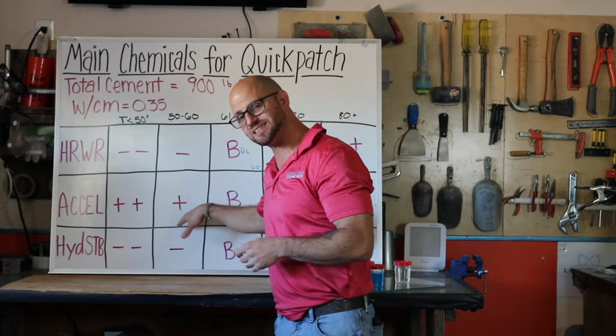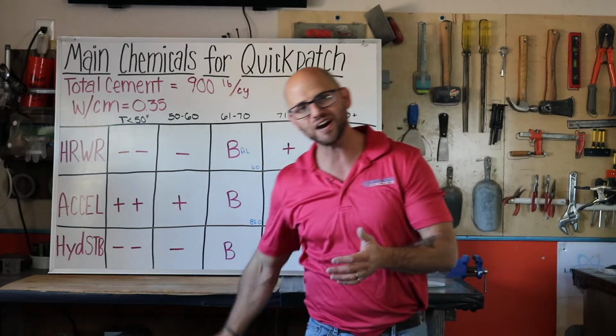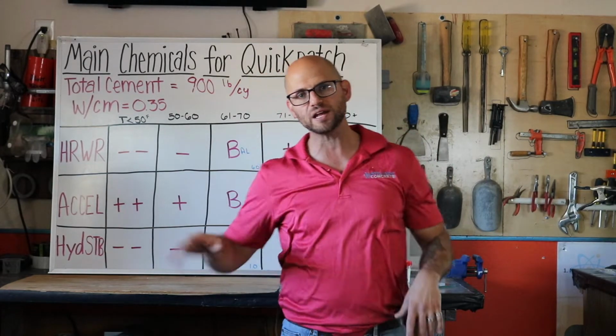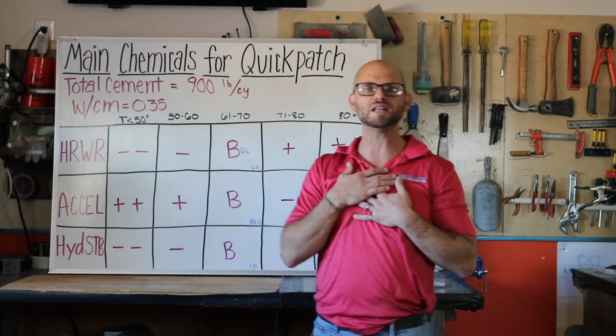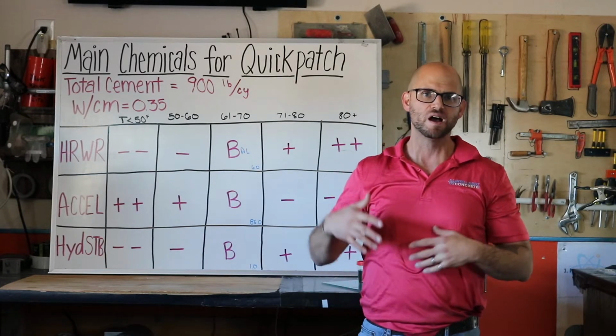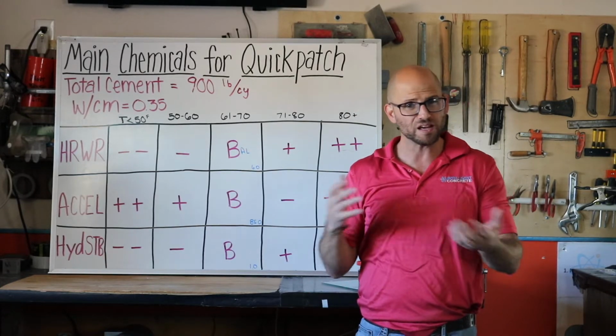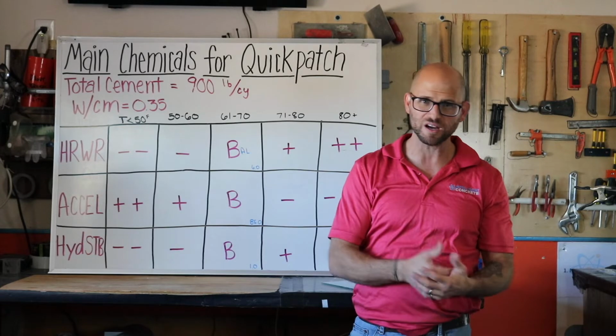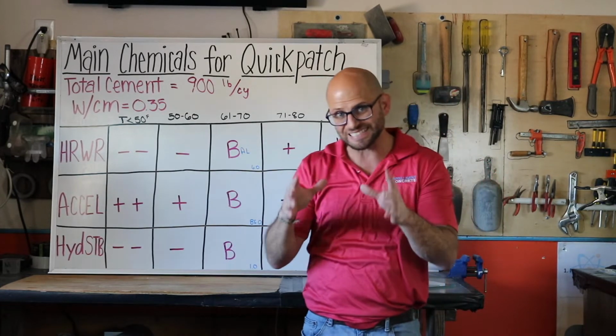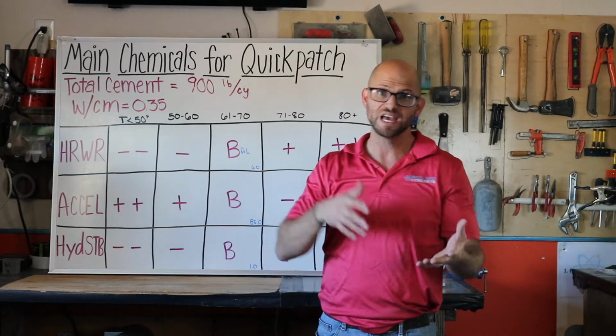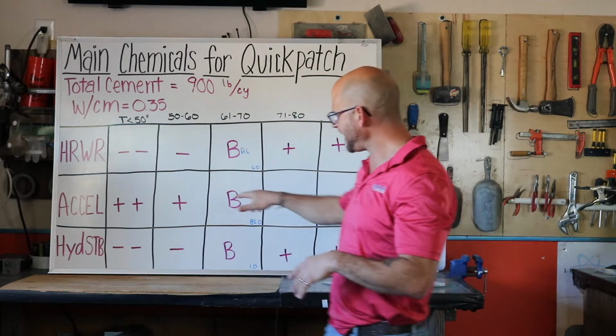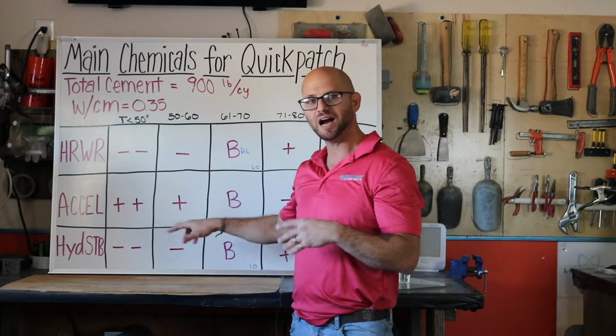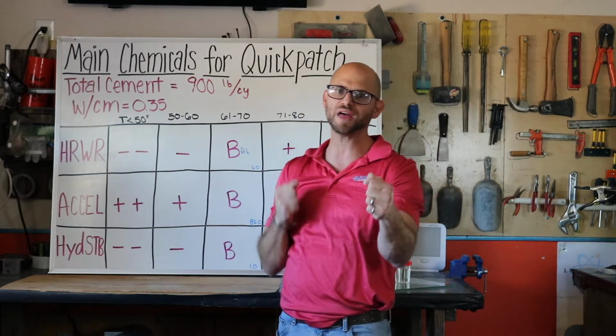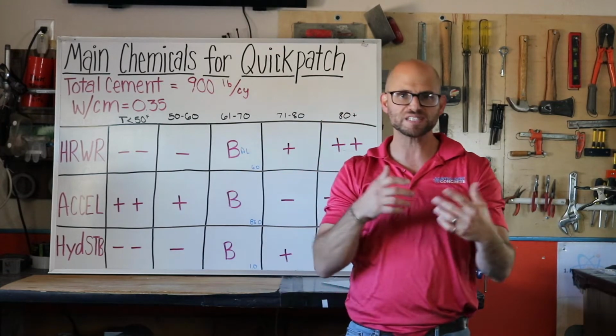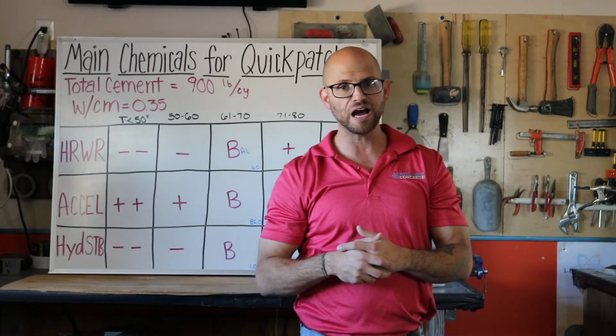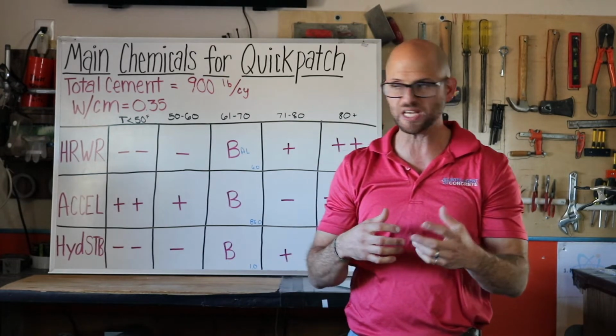That being said, because things aren't taking off as quickly, I've got to add some energy to that, and I do that with adding what I like to call a half a step of my accelerator, and depending on what admixture you're using and the concentration, that step can be anywhere between 5 and 20 ounces per hundredweight. But I take a half a step, and then my hydration stabilizer, I can pull that back a half a step because again, it's colder and I don't need to delay my hydration kinetics.